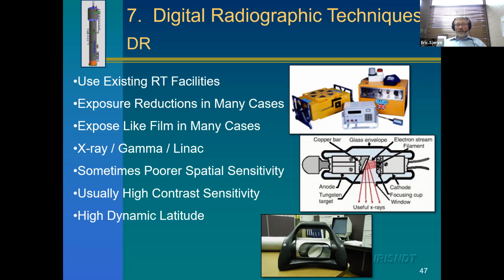So these techniques are done a lot like film. They work with gamma sources like iridium. They work with X-ray tubes. They work with LINACs, which are linear accelerators. We expose them much the same way as film, except we usually get poor spatial sensitivity, and that means we have less ability to find really small defects, but we have really good dynamic latitude and really good contrast sensitivity.